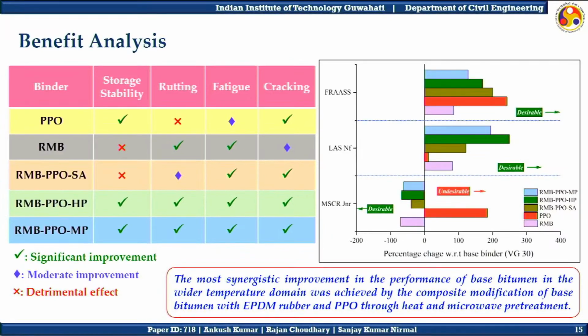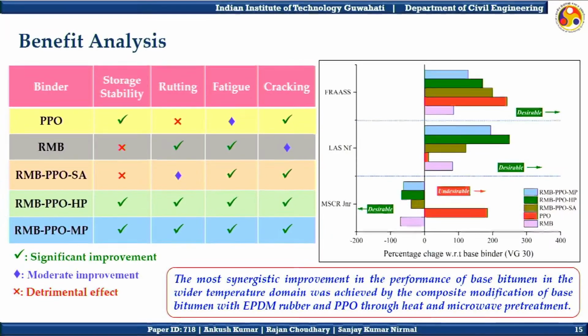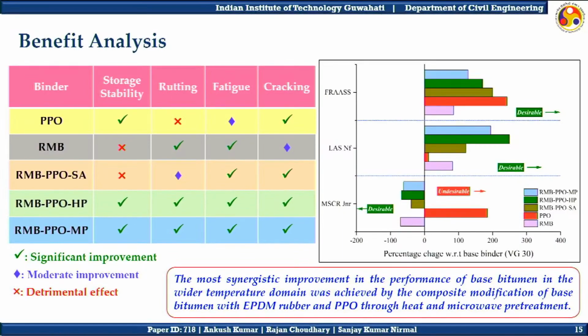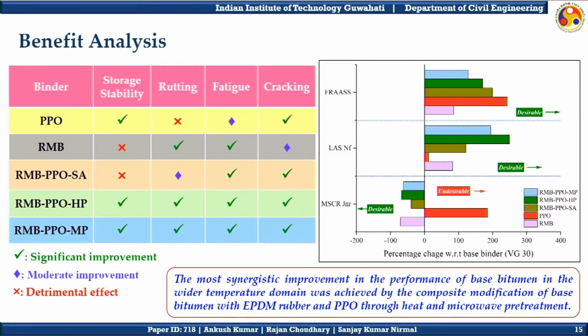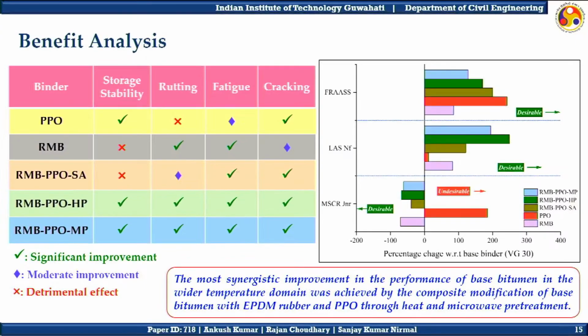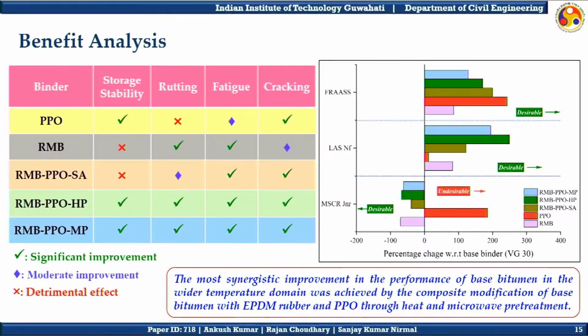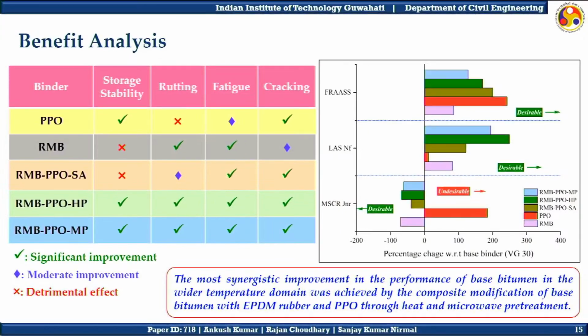In composite modification with sequential addition, the binder was not storage stable and the improvement in rutting was very moderate, and significant improvement was there in fatigue and thermal cracking. While in composite modification after pretreatment through both heat and microwave pretreatment approaches, all those four parameters were improved. So the most synergistic improvement was observed in this composite modification with heat and microwave pretreatment.